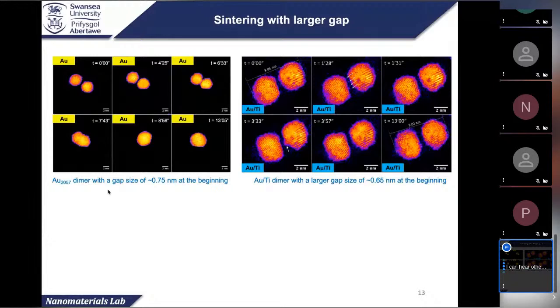In the case of gold titanium, you can see even after 30 minutes, there are still two particles with a gap in between. But what happened during this process is they just exchange atoms in between. From the zoomed-in image, you can see there are a few single atoms in between. Basically, those atoms just jump around and are adopted by the big particle.